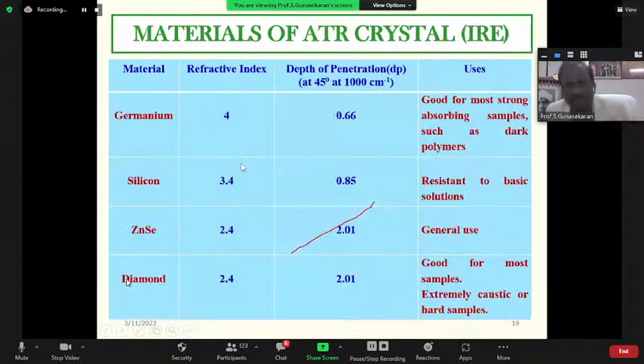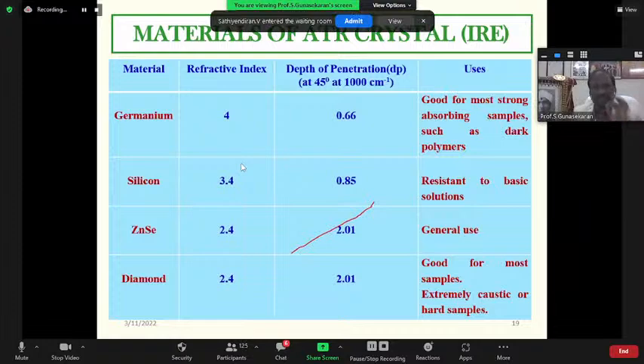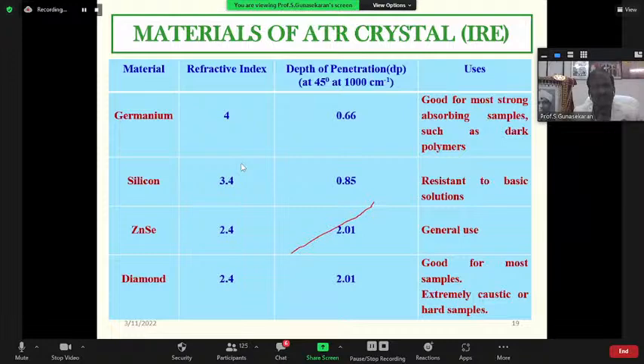Here, friends, what crystals are used as the IRE crystal in our ATR technique? You see diamond, zinc selenide, silicon, germanium. Normally people prefer only diamond because of its best durability and chemical inertness. Whatever chemical you put, it does not dissolve. Best durability, they don't scratch easily. But zinc selenide easily scratches. If scratches occur, we cannot get a good quality spectrum. That is the problem. So we prefer only diamond crystal because of the best durability and chemical inertness.